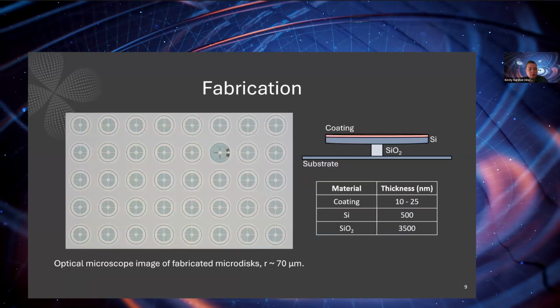So here's an optical microscope image of some as fabricated microdiscs, just to show you what they look like. On the right-hand side, I've got a cross-sectional diagram of these discs with the different materials shown. We tend to put a coating on of thickness, maybe 10 to 25 nanometers, although we could go thicker just by extending the growth time. The silicon layer itself is 500 nanometers thick, and the silicon dioxide pedestal is 3.5 microns tall.